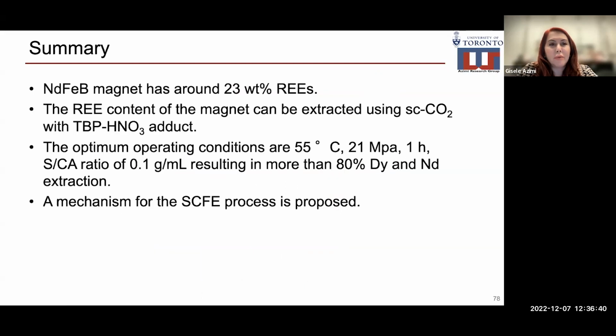In summary, neodymium iron boron magnet has around 23 weight percent rare earth elements. The rare earth content of the magnet can be extracted using supercritical CO2 with TBP-HNO3 adduct. The optimum operating conditions are 55 degrees C, 21 megapascal, 1 hour, creating solid to chelating agent ratio of 0.1 grams per milliliter, which results in more than 80% dysprosium and neodymium extraction. A mechanism for the supercritical fluid extraction is proposed.